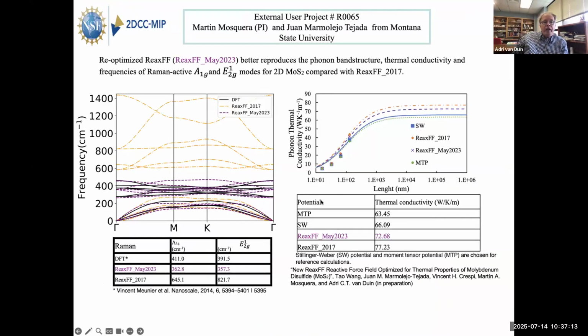To connect with physics, we have kind of ignored phonon distribution in the early stage of reactive description, but we recently found out that we can actually get pretty good thermal conductivity. That can be important, especially when you have high temperature growth on graphitic materials, because that will lead clearly to local hotspots.